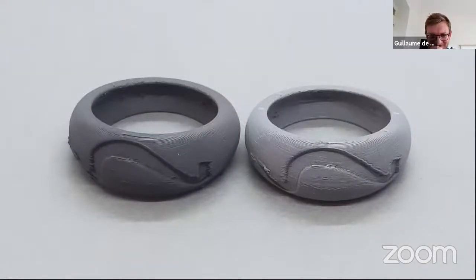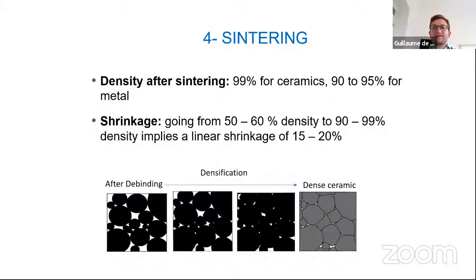Here, interestingly, you can see the part before and after debinding. There's already a very small shrinkage between the two and the change in color, which is really completely normal. But it's usually interesting to see that. Then after we've done that, we're going to go to sintering.